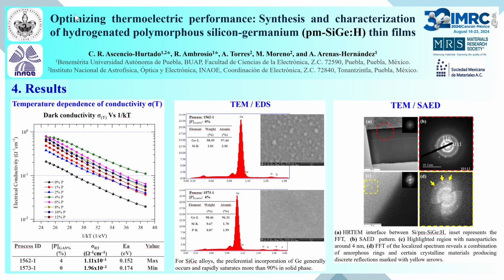On the other hand, the conductivity as a function of temperature and phosphorus concentration is shown in the figure on the left for the range 300 to 460 Kelvin. From these data, the dark conductivity at room temperature was obtained. The activation energy is derived from a plot of log of conductivity against 1 over temperature. We can see the increase in conductivity due to the phosphorus incorporation.